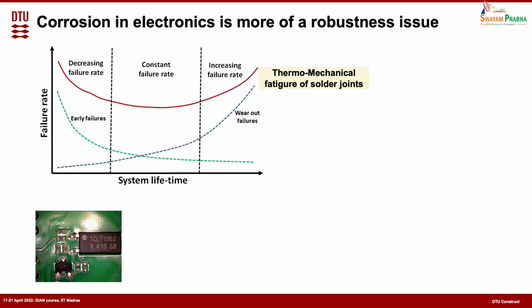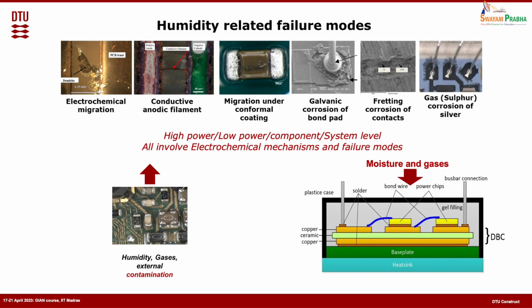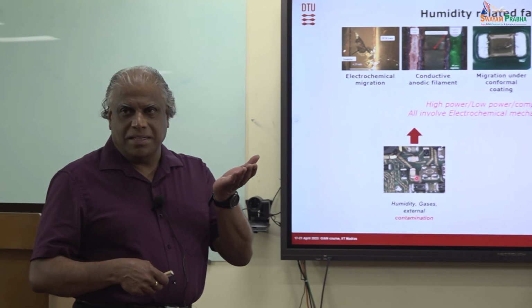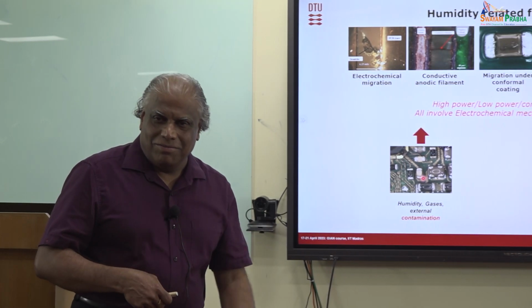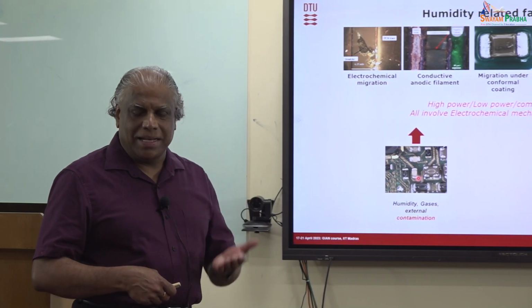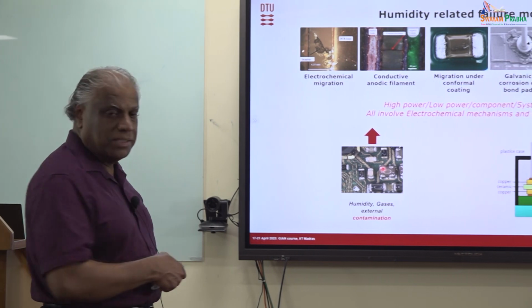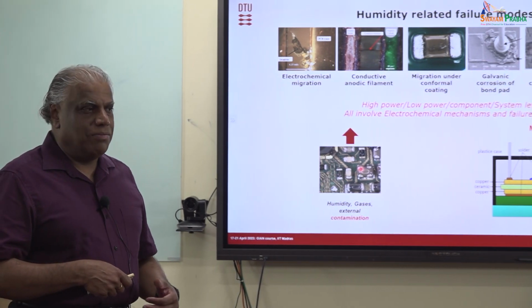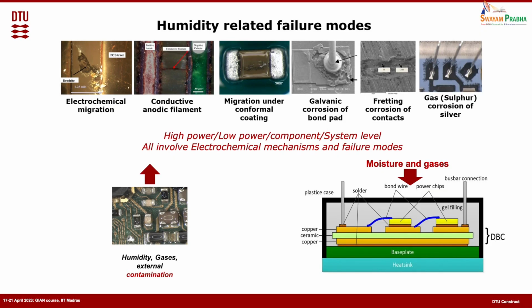biggest problems in electronics is thermomechanical fatigue. That's coming because all these solder joints here have fatigue. When the PCB is working, the temperature increases to say 80 degrees centigrade or 100 degrees centigrade. When the PCB is not working, it cools down, so there is a thermomechanical stress because of the difference in the thermal expansion coefficient. In addition to that, if the PCB is used in a car, it is vibrating, right? So both together will create thermomechanical related failures in these PCBs.